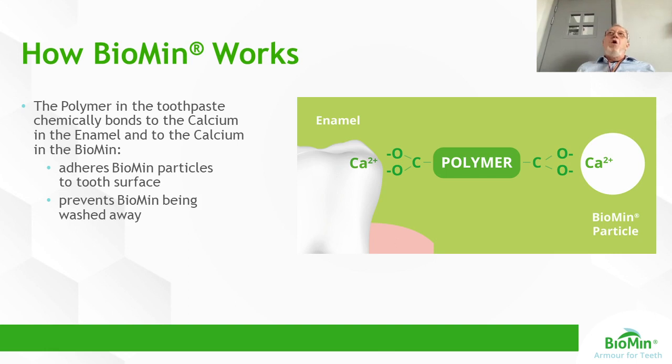When the glass dissolves, it also pushes that pH up. And that is important as well. And it's this combination, really, of delivering calcium and phosphate with fluoride, plus driving that pH up, because driving that pH up also suppresses the dissolution of the enamel.